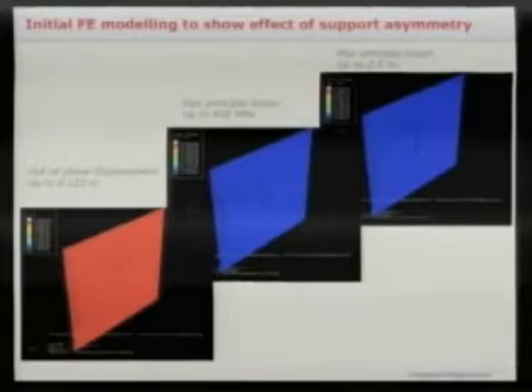Now we can then also model that, and we need to take into account the skin and the core properties and build up a model for the whole of the composite. But also, you need to take into account the way it's attached to the steel cubicle. And because of the slight asymmetry of the setup, we've got more support down this edge than down this edge.